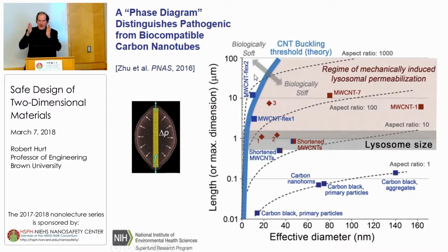And the force used to calculate this is the lysosomal compression force that we have from the literature. And nanotubes on this side would be biologically stiff. So we're proposing that this regime, where you're larger than the lysosome size and you're on the right-hand side of this buckling criterion, you're stiff and not soft in a biological sense, is the regime where you can activate that mechanism. And we've compared with this plot the theory, which is the blue line and this bar, with data.